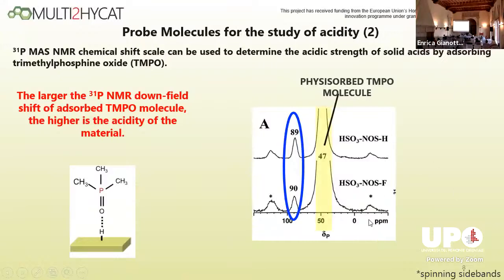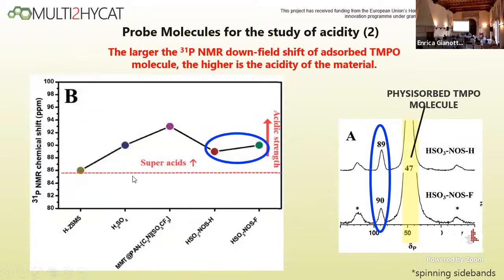So for both our samples, beside a high signal of the physisorbed molecule, we can identify the signal shifted to 89 and 90 ppm respectively for the non-fluorinated and for the fluorinated one. And this is an indication of a superacidity property of the material. In fact, if you go to the literature, you see that when TMPO is interacting with a superacid, the shift should be at ppm higher than 85. And as you can see in this image, both our samples, the non-fluorinated and the fluorinated one, have an acidity that is close to that of sulfuric acid, with a slightly higher acidity for the fluorinated one.